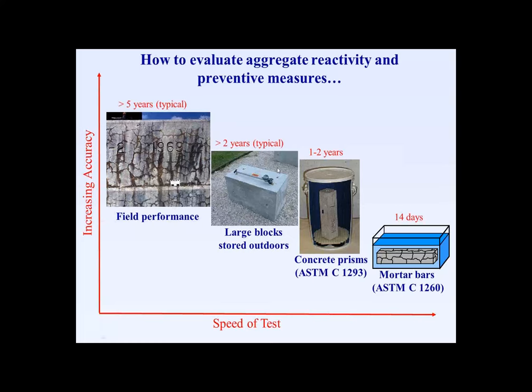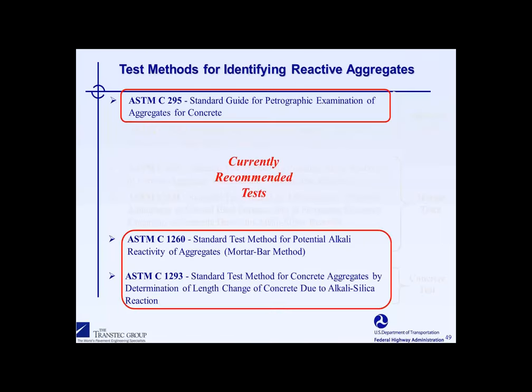We start going down here to the concrete prism test. The accuracy is getting less because of leaching, and the speed is getting a little bit more rapid. But our most rapid test is the accelerated mortar bar test here, which is typically done in 14 or maybe 28 days. But again, the accuracy of that test with many aggregate types can be called into question.